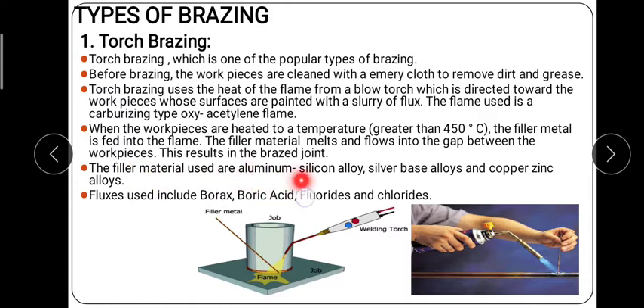The filler materials used are aluminium silicon alloy, silver base alloy, and copper zinc alloys. And the flux used for reducing the oxidation and cleaning the surface is borax, boric acid, fluorides, and chlorides. So this is torch brazing, which has the same working principle as torch soldering.